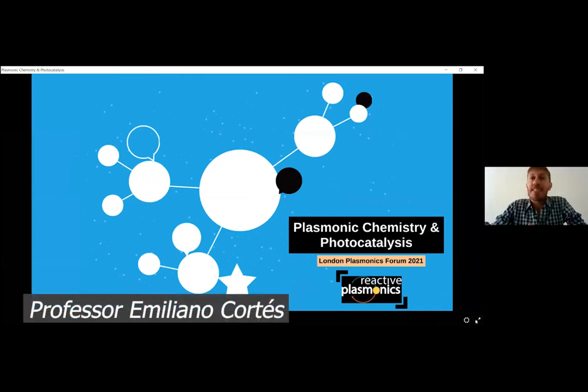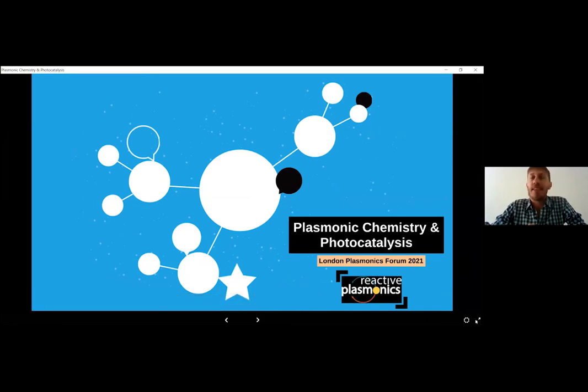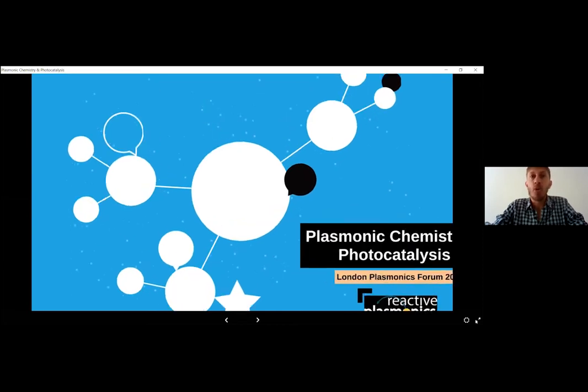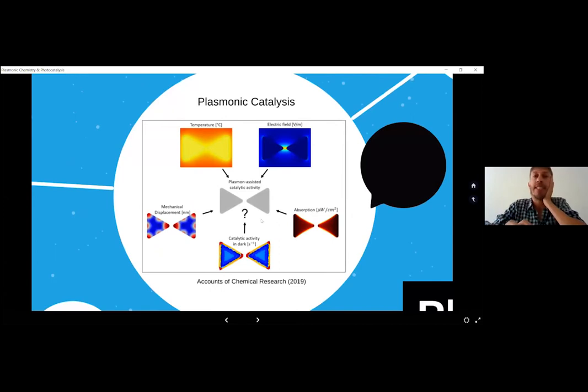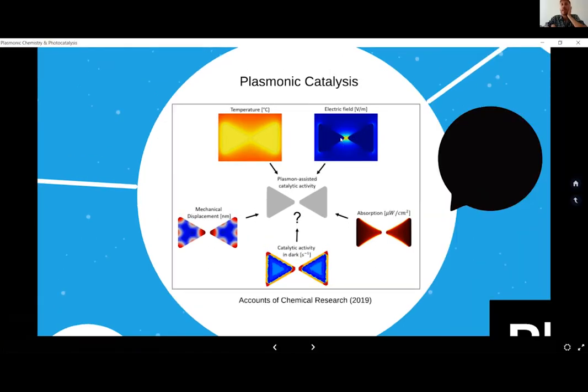So I will present briefly some of the highlights on these 6 years in reactive plasmonics on the side of plasmonic chemistry and photocatalysis. So let's start from the very beginning and the idea of using these plasmonic materials for catalysis or for doing chemistry. And for that, I think it's first important to check the properties of these plasmonic nanoantennas when they are being illuminated towards chemical reactions, right? If we think on these plasmonic interfaces, so here we have a bow tie antenna that is being illuminated, many phenomena happen at the same time on these antennas when we are illuminating with continuous wave lasers. On the first hand, we have electric field confinement in these antennas, in these kind of hotspots, which is a very well-known effect of plasmonic antennas for a very long time.